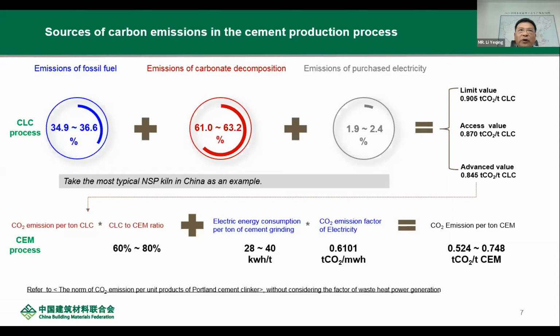When we use this clinker to produce cement, we assume the clinker factor is 60 to 80%. So the emissions from the clinker are 516 to 688 kilograms. The power consumption of the grinding is a different system, but the range is between 28 to 40 kilowatt hours per ton of cement. So emissions from this side are 17 to 24 kilograms.